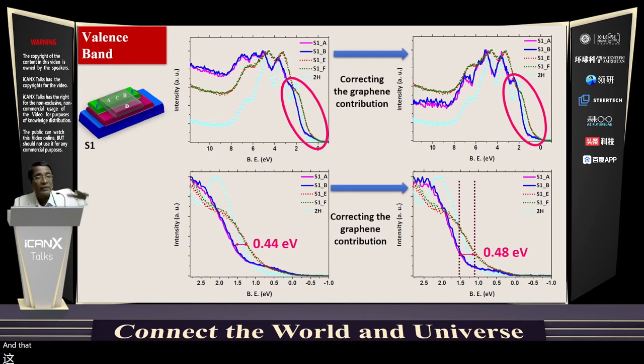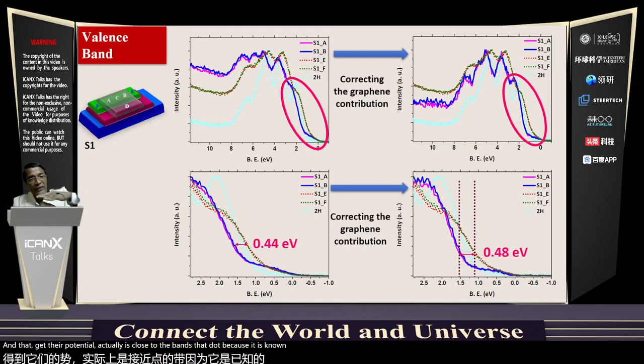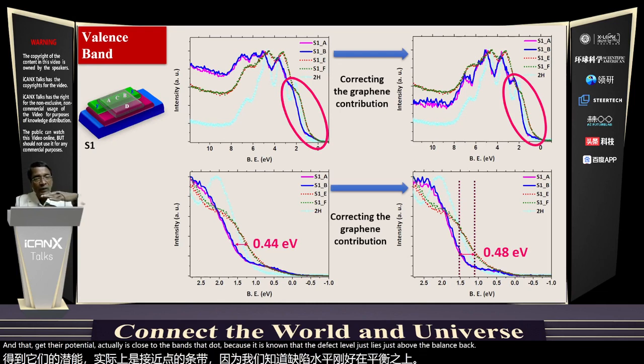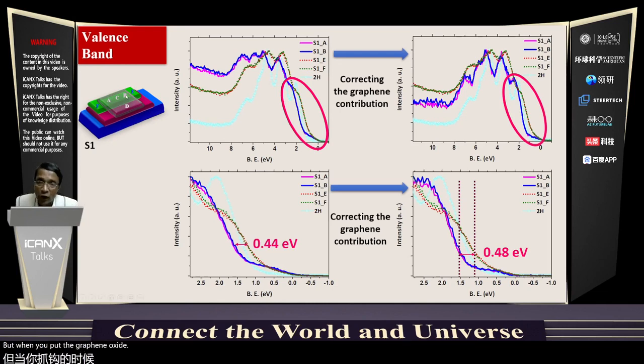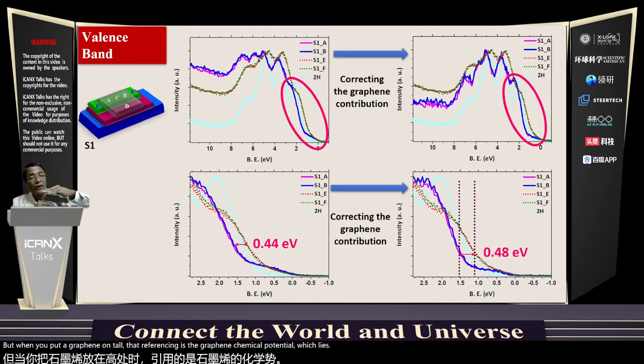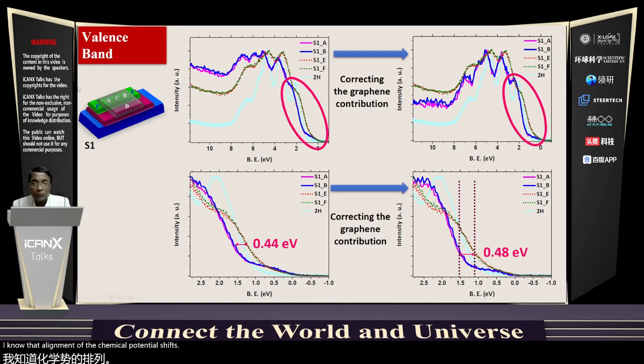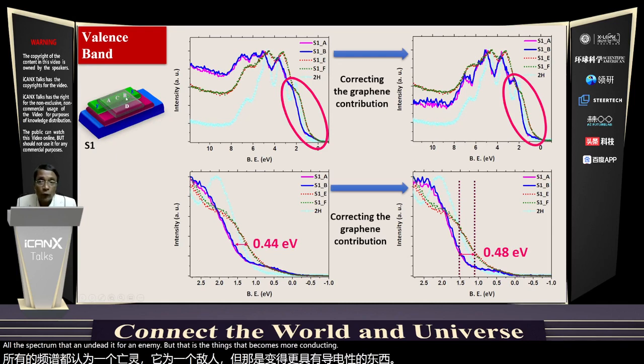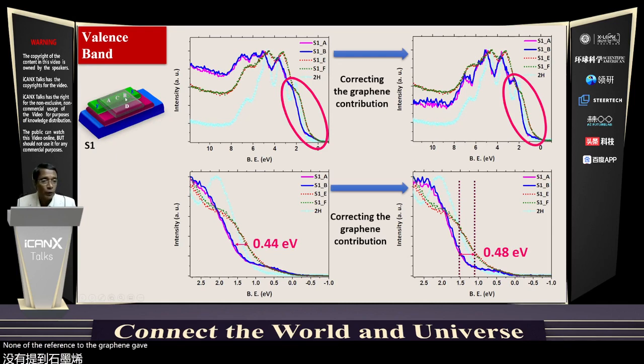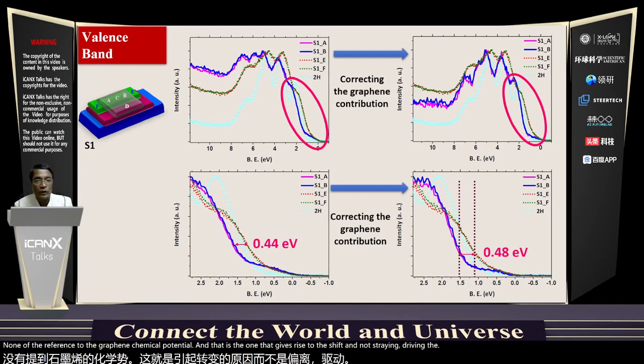And that chemical potential actually is close to the valence band top, because it is known that the defect level just lies just above the valence band. But when you put the graphene on top, the referencing is the graphene chemical potential, which lies further above. And the alignment of the chemical potential shifts all the spectrum that are under it further away. But that is the phase that becomes more conducting. Now your reference is the graphene chemical potential, and that is the one that gives rise to the shift, and not strain driving the formation of a metastable state.